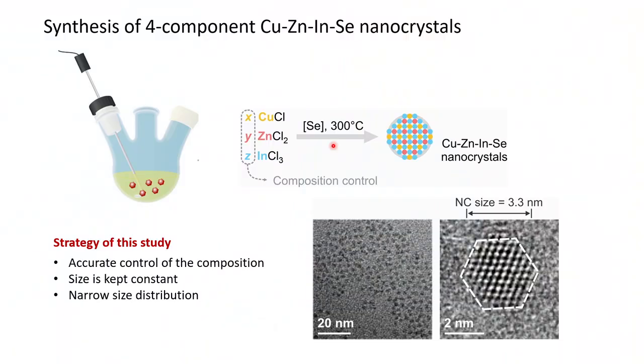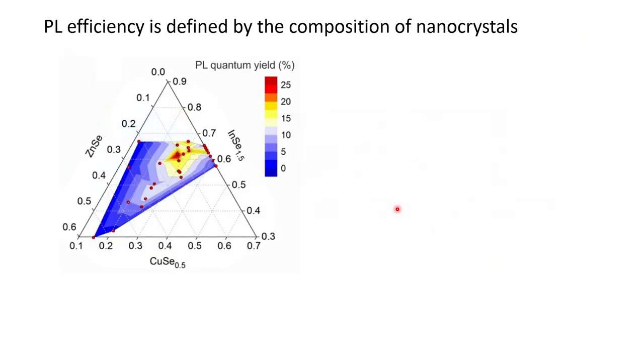So the strategy for this project was like that. We decided to mix the elements and to tune the composition of these elements in the form of nanoparticles. To simplify it a little bit, we fixed the size of these nanocrystals always to be about 3.3 nanometers. So we see from the TEM image, they have a narrow size distribution, they are 3.3 nanometers, only composition is tuned. And so we decided, let's see if we find something interesting in terms of composition and properties under quantum confinement. And that's what we found.